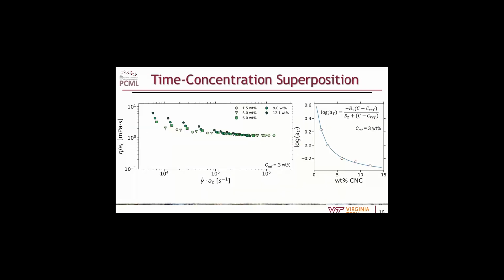We tried to do time concentration superposition on this, following the same principles as time temperature superposition, to extend our range and see if we could estimate higher shear rates by using a higher concentration at a lower shear rate and then shifting it.